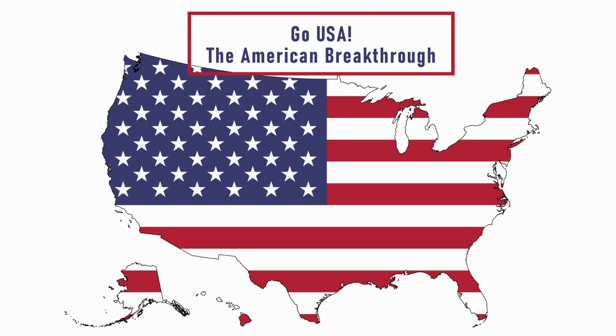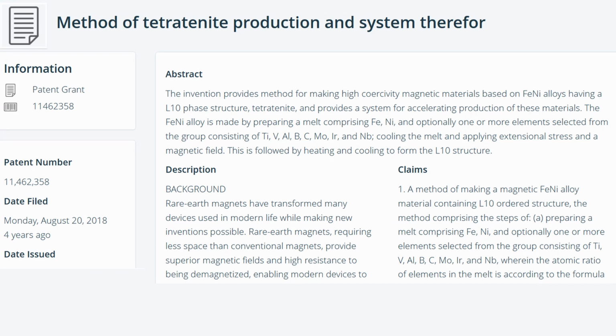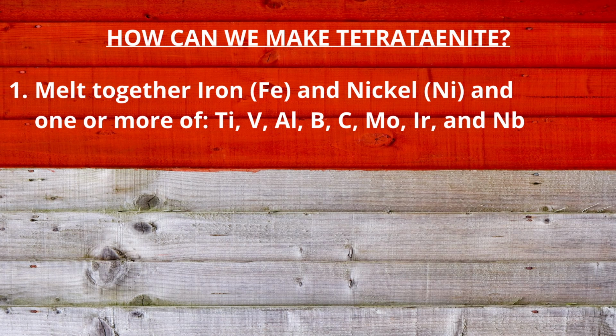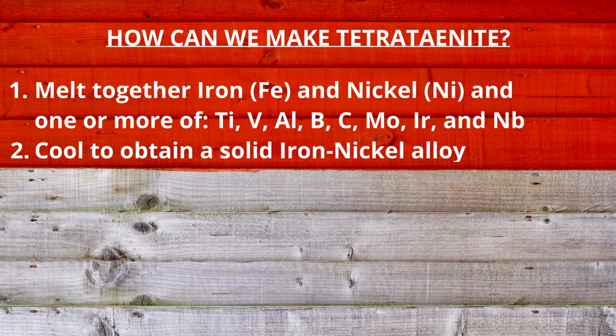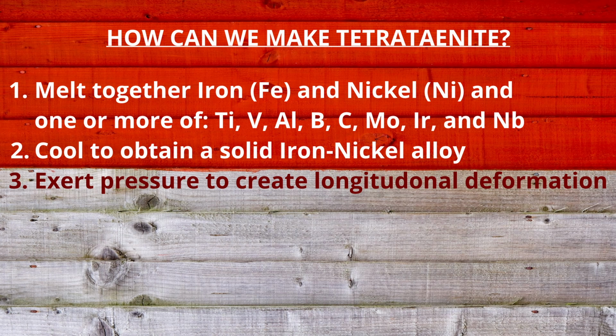The first method, developed by researchers from Northeastern University led by Professor Laura Lewis, is described in U.S. Patent Number 11462358. This method is performed as follows. First, iron, nickel, and one or more elements from the list shown on the screen are melted together. The melt is then cooled to create a solid iron-nickel alloy. When the solid is below the chemical ordering temperature of L10 tetrataenite, pressure is exerted on it to create a plastic deformation in a longitudinal direction.